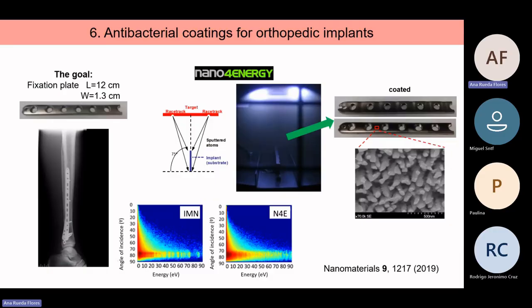You can do it, but then you need a good collimator, because at the end, you have to define a tangent. Then you need to collimate a lot, and then you need a motor and so on. So it complicates the deposition a lot. But in this case, these implants are used when you break, for instance, your leg skiing, both the tibia and the fibula, and you have an open fracture. For a typical hip implant, the rate of infection is about 3 to 5%. So let's say 1 in every 30, 1 in every 20 is infected.